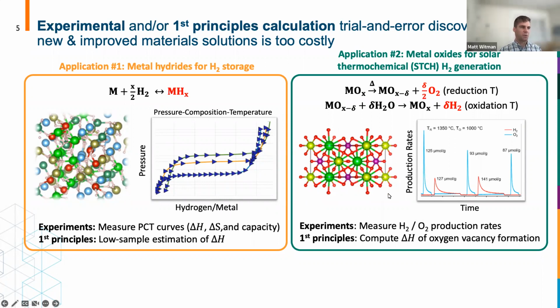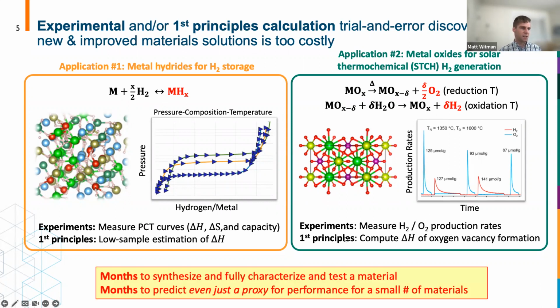So again, experimentally, we can directly measure the material, the most important material properties, which are, of course, this performance here. But again, it takes a long time to do these experiments. And from a first principle standpoint, we certainly can't simulate these cycles from first principles, or at least it's very difficult. And instead, what we typically rely on is computing or estimating the vacancy formation enthalpies. And again, that's not really possible to do in super high throughput at the moment. So we've run into these barriers where we want to test or have these optimal materials, but it takes too long to make them and test them.